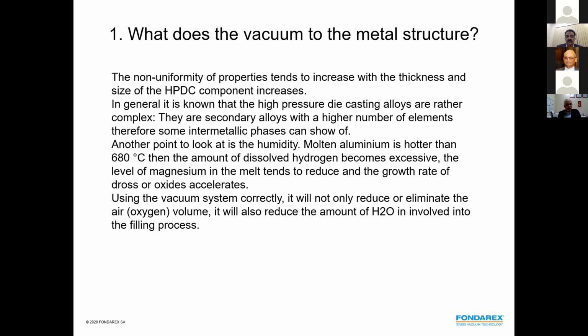So if I go a little bit further, the non-uniform properties tend to increase with thickness and size of pressure die casting components. And therefore, if we have thicker parts, the solidification becomes even more important. Therefore, the vacuum is also important, because once we have a perfect filling, the solidification is getting more precise, and therefore we also get better microporosity. The secondary alloys we are talking about have some elements of intermetallic phases, and sometimes, of course, oxidation comes up, and also we can see water elements, H2 elements, which are included in the excessive hydrogen in the melt.